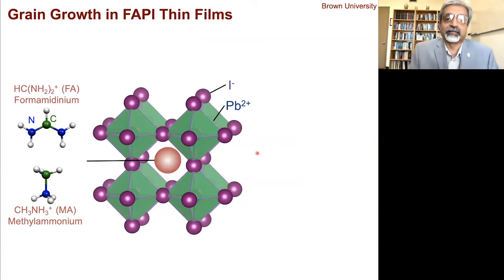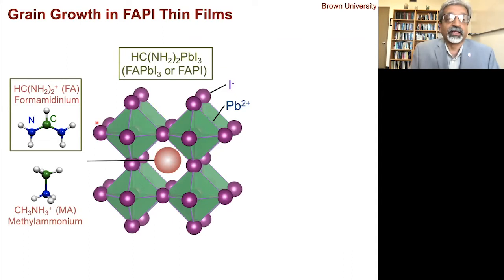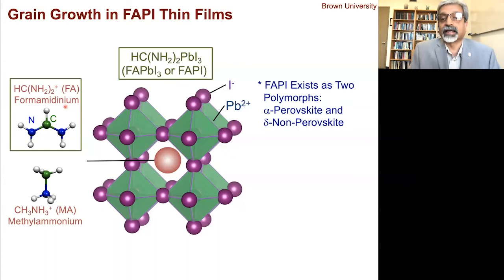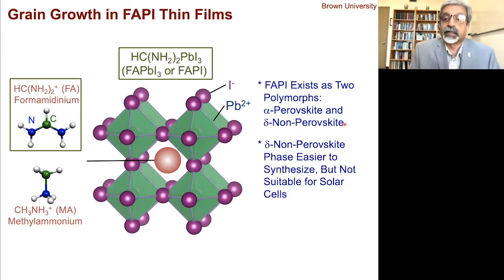But there's a problem. The problem is that the grains don't like to grow in thin films. So when they reach the size of the thin film thickness, they stop. And so here we're going to use FAPI, and FAPI is formamidinium instead of methylammonium. What is unique about FAPI is that it actually has two polymorphs. MAPI only has one polymorph at room temperature. One is the alpha perovskite, which is what we need for solar cells, and the other is the delta non-perovskite, which is not very useful, right? And as nature has it, whatever is useless is always easier to make, right? So delta non-perovskite is easier to make, but it's not very useful.